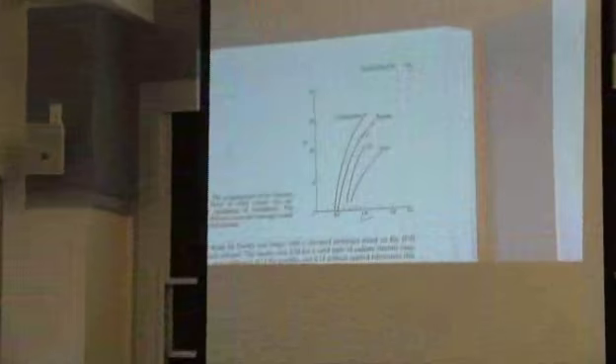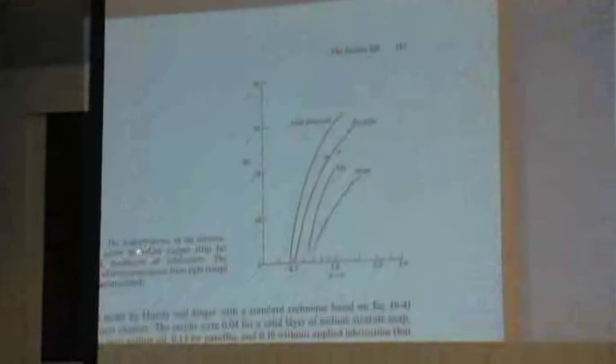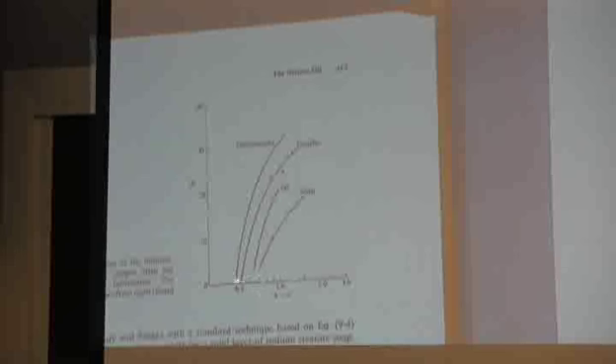So this is out of Backofen, and this basically shows you the delta dependence of the inhomogeneity factor for copper strip with different types of lubrication. So here's delta, and this is basically copper strip where delta equal to 1 means the height and the width of the deformation zone are equal, right? Here you're really in a rolling situation. Over here you're starting to get to something a little more towards drawing or extrusion. In any case, you can change the die angle of the draw, right? Anyway, unlubricated, the inhomogeneity factor increases as you get to higher and higher delta.